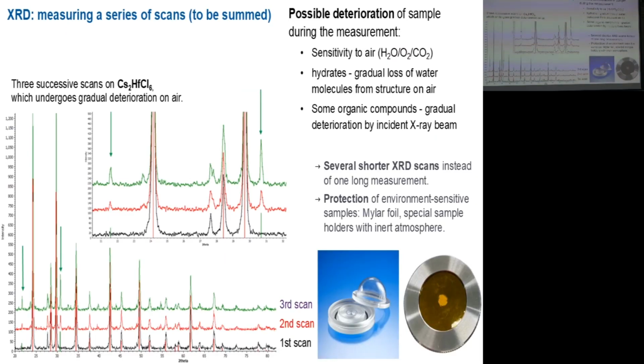Then another issue which you can encounter during XRD analysis: some samples won't be stable in air because of moisture in air. They will become hydrated because they are hygroscopic, or they will react with carbon dioxide, forming some carbonates. Or maybe you intend to work with, for example, metal iron nanoparticles, which will basically burn in air. So there can be different issues causing the air sensitivity.